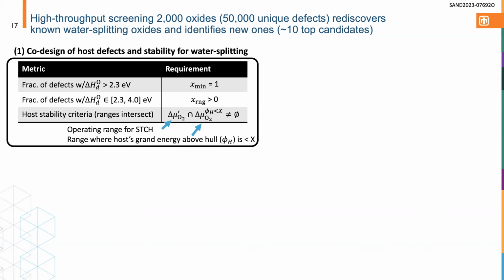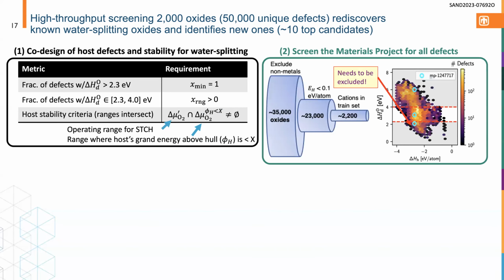on which it operates. So you basically need to confirm that the material stability in the grand canonical ensemble, right, when it's open to an oxygen chemical potential, is that the material will be stable and that range intersects the target range for STCH. Okay, so if you do that, you can screen all of Materials Project.